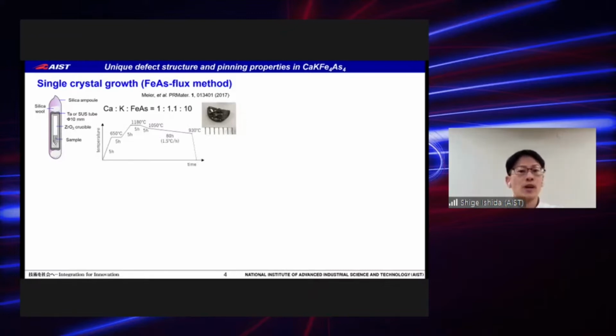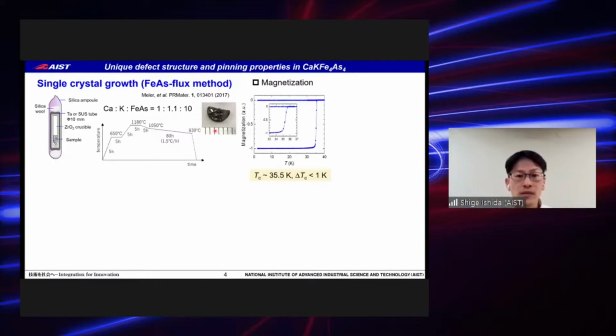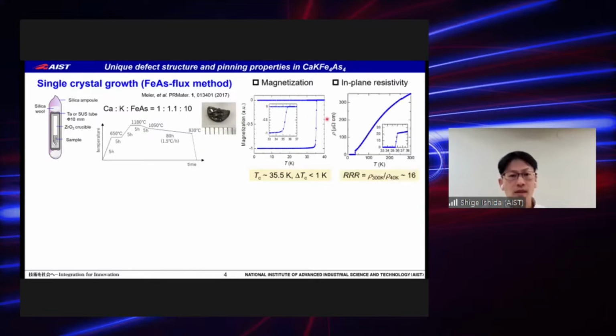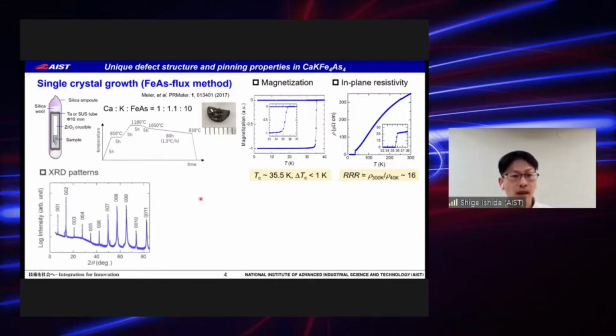Single crystals of calcium potassium 1144 were grown by the iron arsenide flux method following the Meier's work. The grown crystal looks like this, and a sharp superconducting transition was observed by magnetization measurement, and the in-plane resistivity showed a high residual resistivity ratio, around 16, which indicates the high quality of those single crystals. The XRD pattern only shows 00l peaks of calcium potassium 1144, namely there are no trace of 122 phases.